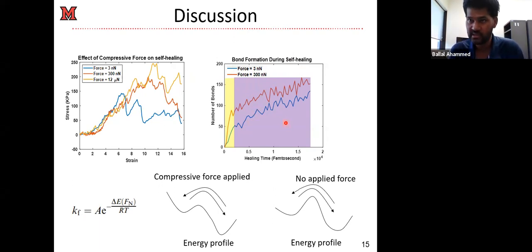Now we can think in terms of the classical Arrhenius picture that we studied in our first-year chemistry courses. We know that for a reaction to happen, there is a potential energy barrier. When you apply the force, you are reducing this energy barrier, reducing the activation energy, which makes life a little easier for the crosslinkers to come together and bond. So the compressive force is changing the energy landscape and allowing bond formation to be easier. The rate of forward reactions from the Arrhenius-type equation depends on the delta E, the activation energy barrier, which is a function of the compressive force. So this energy barrier can be engineered using the compressive force, which helps the reactions to be faster, accelerates the self-healing process, and helps the material recover its properties so well.